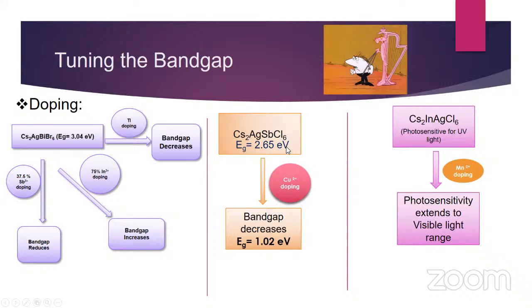You can see here Cs2AgSbCl6, which has a band gap of 2.65 electron volt. Then with copper, the band gap decreases to around 1 electron volt. And here you can see Cs2InAgCl6. This material is photosensitive to UV light, and if you dope it with Mn2+ cation, then it shows photosensitivity in the visible light range. This happens because after absorbing the UV light, this Cs2InAgCl6 double halide perovskite transfers the excitation energy to the d electrons of Mn.